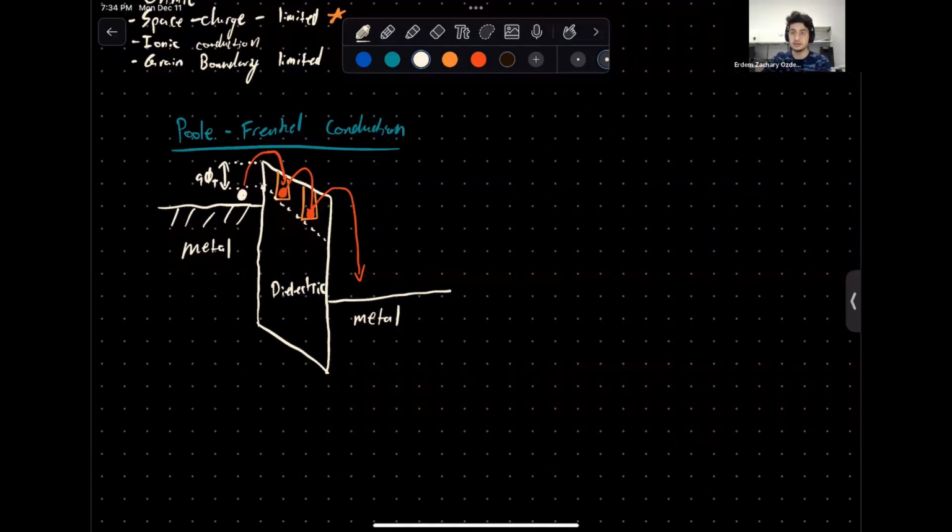So if we're continuing off of this aluminum nitride example, we can think about its defect chemistry and let's say nitrogen vacancy, which might sit at around 0.3 eV below the conduction band. And so if we end up getting hopping based on a 0.3 eV activation energy, then we can tell from that potentially we have electrons hopping through nitrogen vacancies down to the metal.